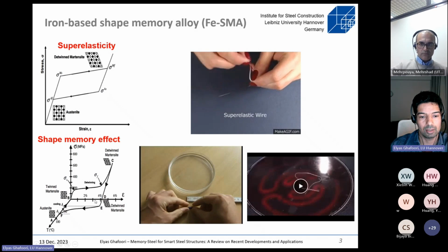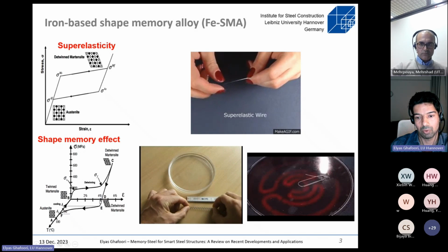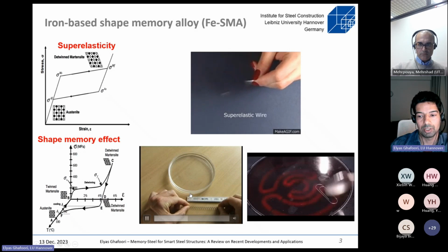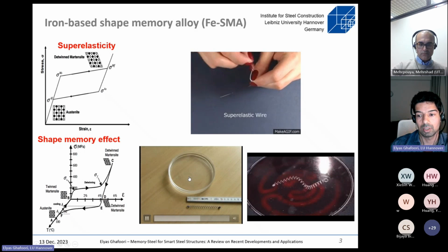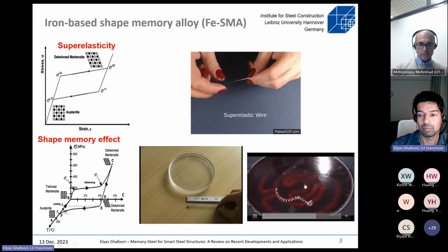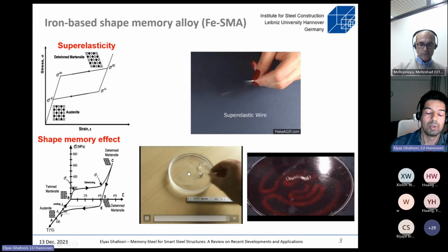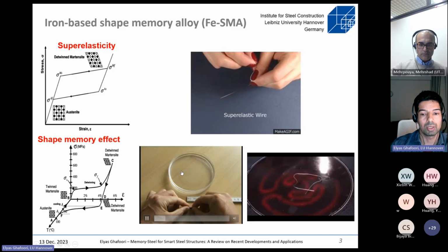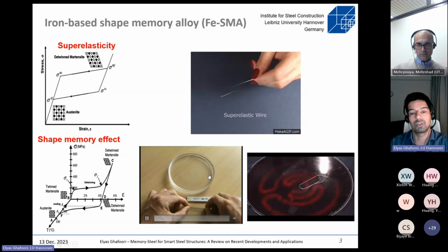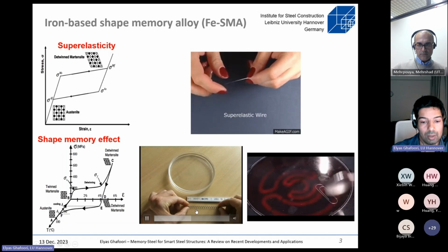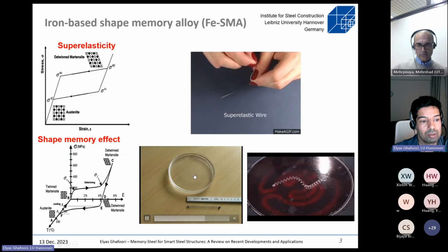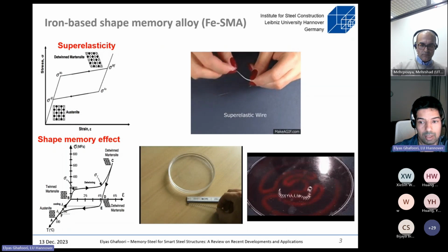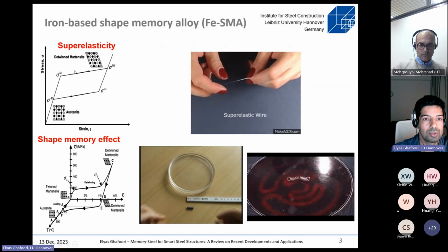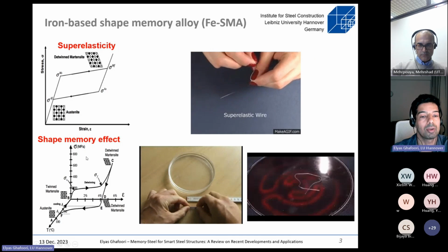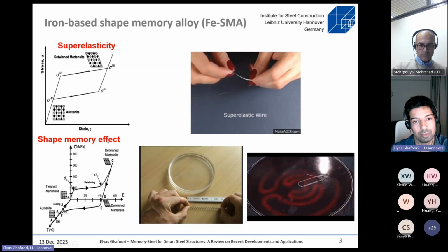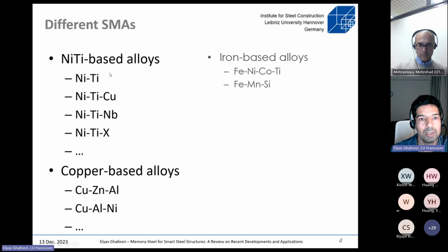That means that we pre-strain the shape memory alloy, and then after heating here with hot water and here with temperature, they can actually recover their shape. So during the pre-straining, the material is changing from austenite to martensite phases, and during activation they change from martensite to austenite. So the last speaker talked about mainly superelastic behavior, and now I'm talking about shape memory effect. So it's actually complementary, right?